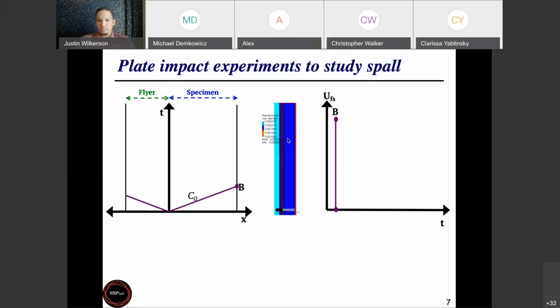This is actually a full 3D calculation, and so the shock front can develop whatever complex spatiotemporal form that it wants, but you can see that it's propagating in a nice one-dimensional fashion. Out towards the edge, there may be some edge effects, but for the most part, this looks really one-dimensional. Whatever's happening here is happening the same up here. That's one of the things that we really like about plate impact experiments: they're nice and one-dimensional, and then we can do some really simple one-dimensional analysis to back out what's going on in the material.